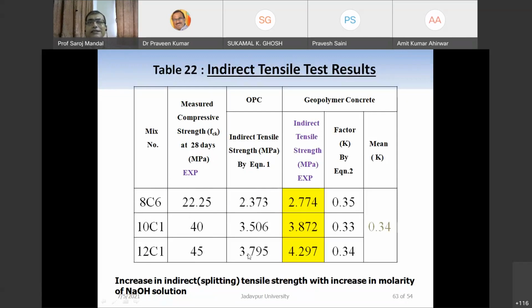Now this is the indirect tensile strength by equations. By equations means if we use OPC, that is, if we consider the equivalent of this FCK in terms of normal concrete, what should be the equivalent tensile strength in concrete? The indirect tensile strength we get experimentally is comfortably higher in terms of geopolymer, and the average factor comes to 0.34, which is higher than 0.3.